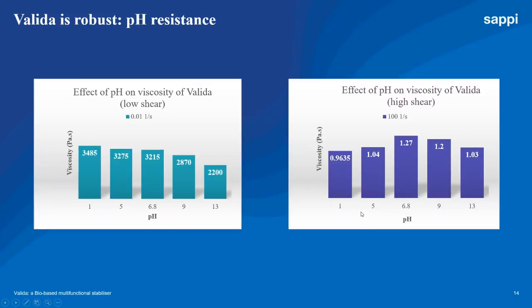On the left graph, we have the low shear zone, and on the right graph, we have the high shear zone. At low shear, we notice a very good viscosity thickening effect at pH 1, for example, and a slight drop at pH equal to 13, but still a very good viscosity in this case. While at high shear, basically the viscosity is independent of the pH.